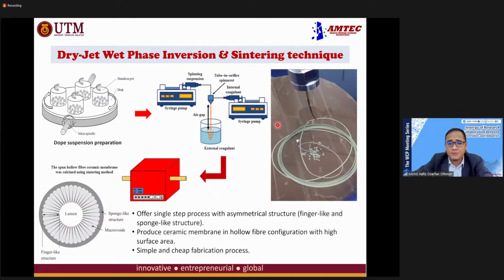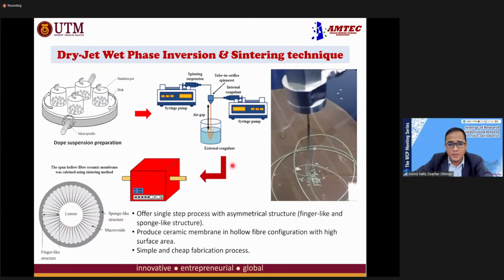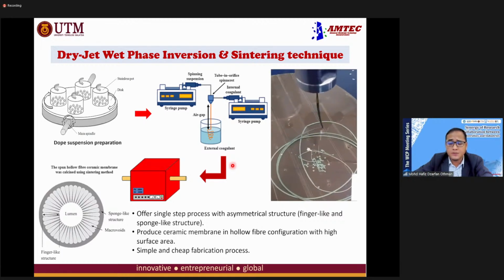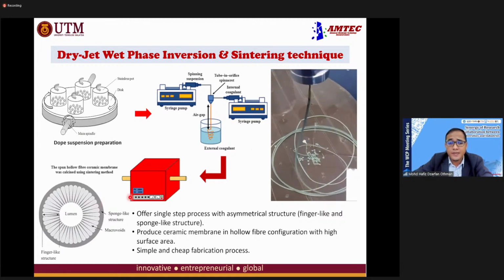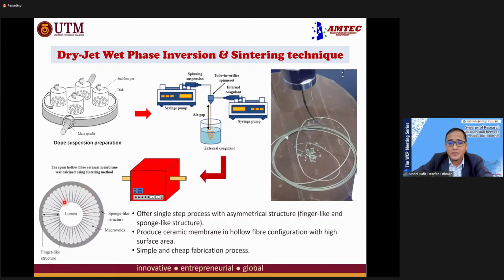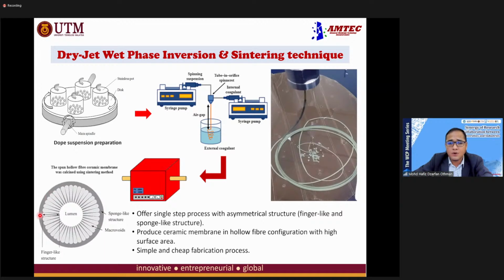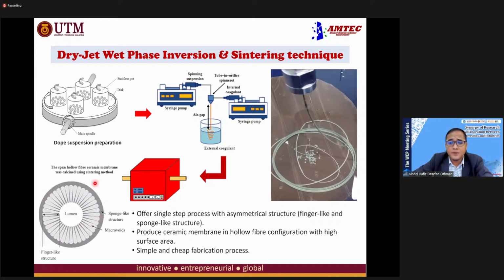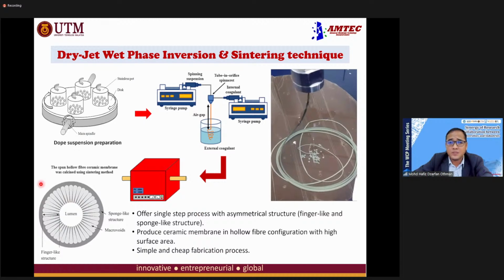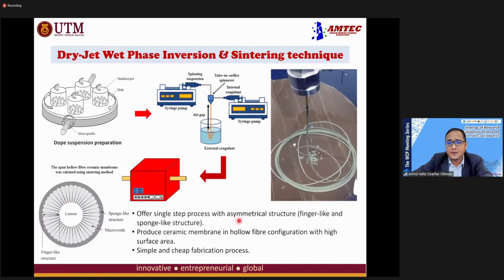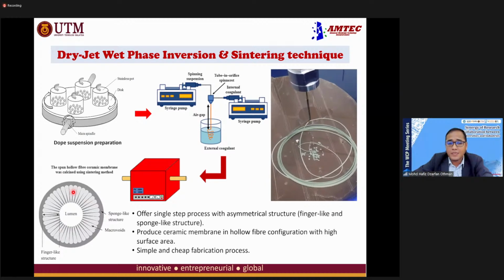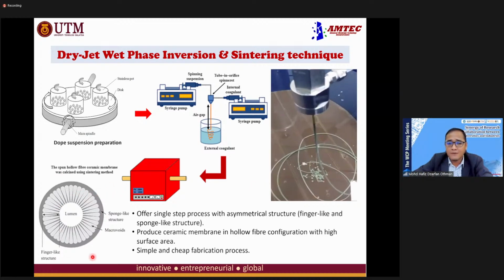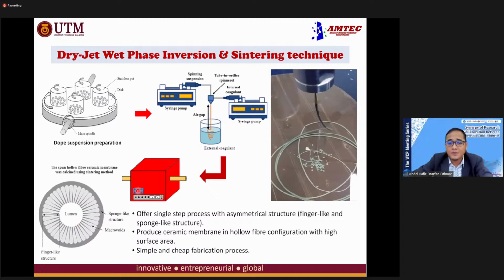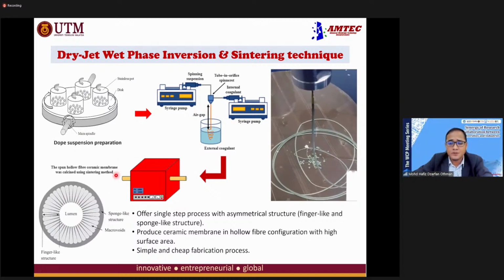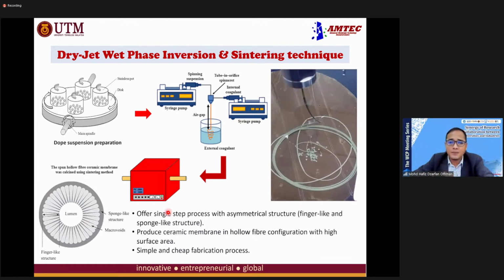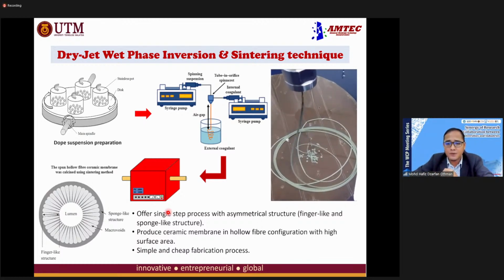Because of the interaction between the internal coagulant and the dope solution, the suspension, it will create a finger-like structure. This combination of finger-like and sponge-like structure is what we call asymmetric. So we can produce an asymmetric structure in a single step by using phase inversion. But we have to know that in the precursor we also have the polymer binder, so we have to burn off the polymer binder by using the sintering procedure. This sintering procedure will also turn the precursor into a very strong ceramic membrane.